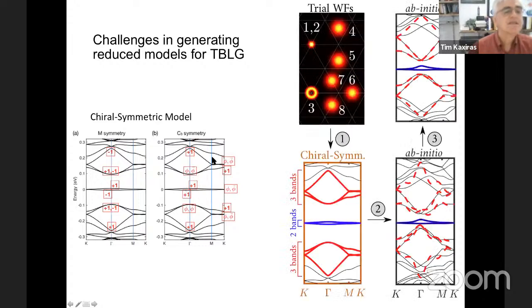Then we use as guess states that come from this model and use these to project the ab initio bands. So these are the bands that I just described to you that come from the ab initio Hamiltonian model, and we try to fit by producing a model with a few bands that captures the ab initio band structure with full atomic relaxation. So we start with these states that are inspired by and include the symmetries of this model, and they are centered at the following positions. So there are two states with different symmetry, S and P-like symmetry, at the AA regions. These points are the AA regions. Then there's a third state with S-like symmetry, which also has its center at the AA region.